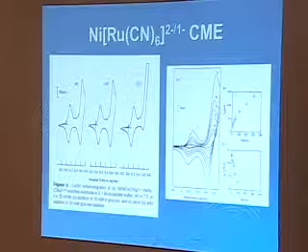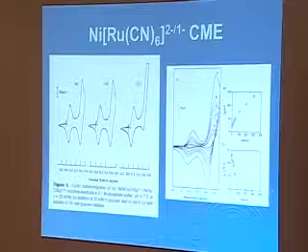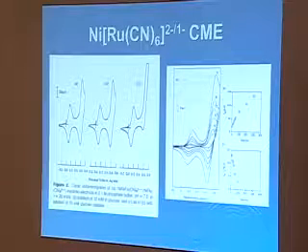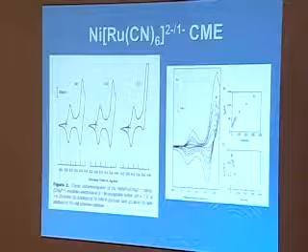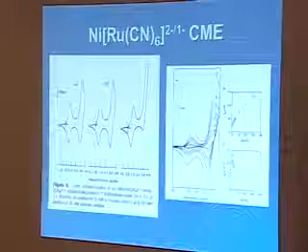Well, you can't tell if it's reversible or not. I'll tell you, it is reversible. We have some scan rate data over here, for example. But now there's a different problem. I've got an inner layer. Stepwise, I took a nickel electrode and reacted it with ferricyanide, and checked to see that I put a layer of nickel ferricyanide down.